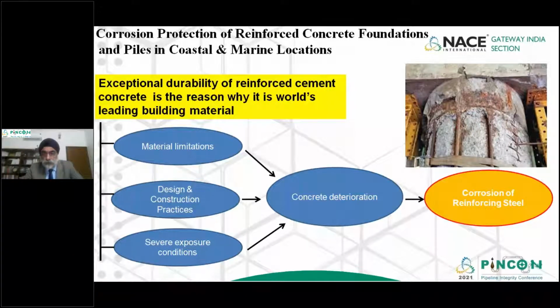So in the photograph on the left-hand side, you can see the cover of the concrete has completely gone. The rebars are exposed to the environment. In this particular photograph, the rebars are exposed to the atmospheric environment, which also causes a high corrosion rate. So this is the process which, as professional engineers, we have to stop. That means we have to stop the steel reinforcement in the concrete from corroding, to ensure the integrity of the pile caps, pile foundations, and equipment foundations in coastal and marine locations.